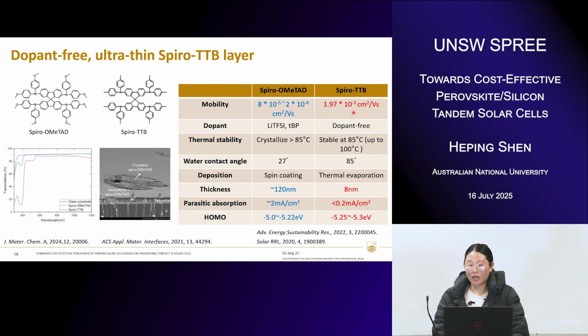It has one to two orders of magnitude higher mobility. That means we have the potential to have conductive HTL layers based on this material without any help from the dopant. So it addresses a lot of the stability issues from the dopants. It's stable up to 85, which is the temperature we usually see for the solar module, and can be up to 100 degrees, which of course needs to be further assessed.